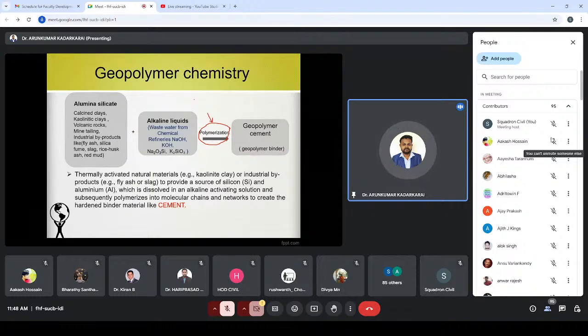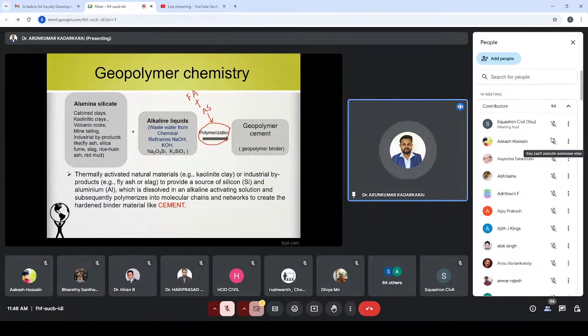Geopolymer was first invented by Davidovits. The professor introduced using fly ash as an aluminosilicate binder and added alkaline activator solutions, and they mixed together and formed a gel, but it did not harden. It remained pasty in nature. So he cured the samples by heat curing, elevated temperature curing, to speed up the polymerization. He achieved the polymerization and finally got the geopolymer concrete.